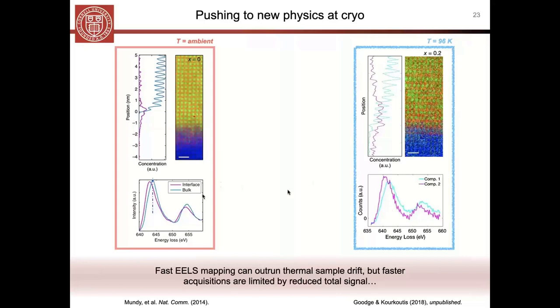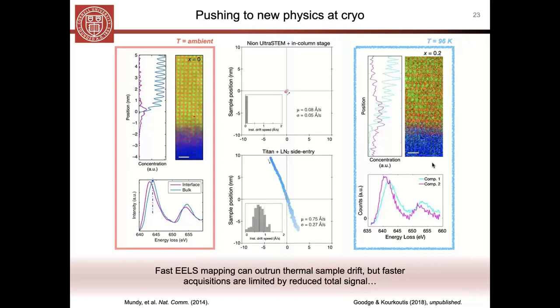Things at first glance look pretty similar to the room temperature, but you'll notice that if you compare the fine structure, especially here, the signal to noise is not quite comparable. And this was the best that can be done at room temperature. And if you'll believe it, this is the best we've been able to do so far under cryogenic conditions. The reason for that is really just a dramatic difference in the experimental setups that were used to take this data.